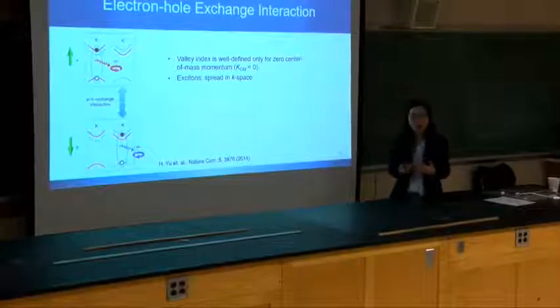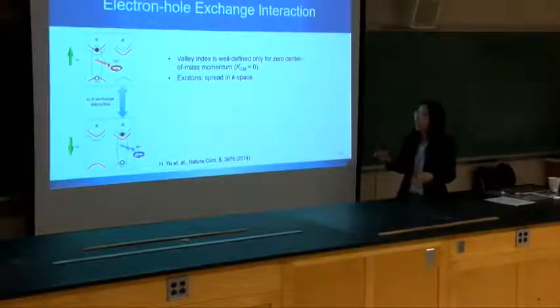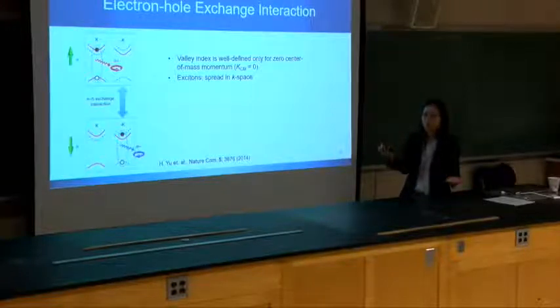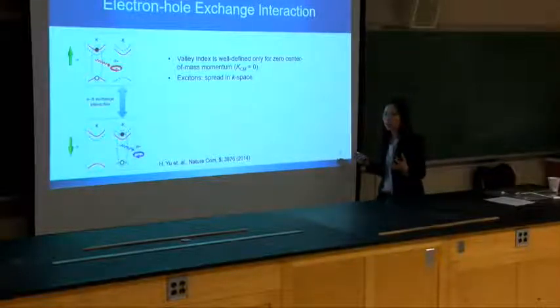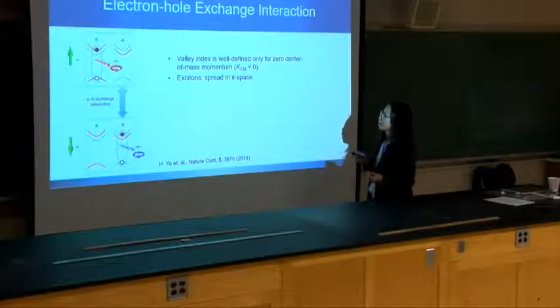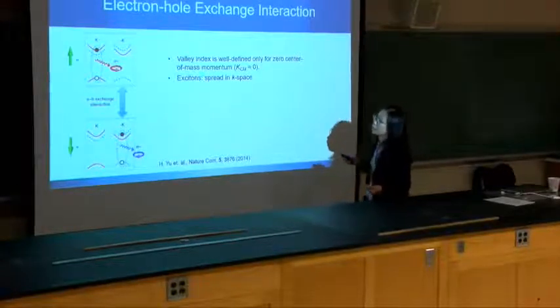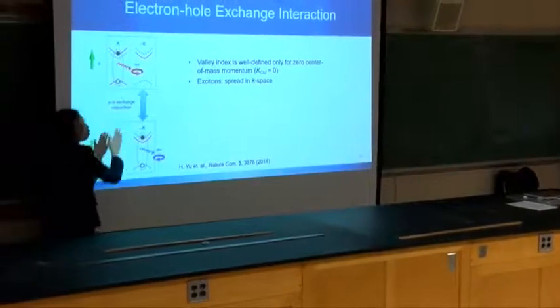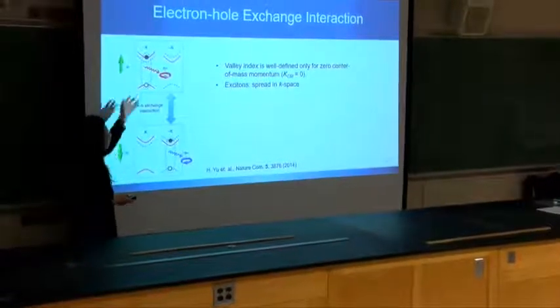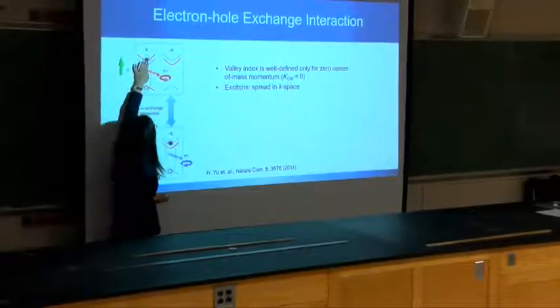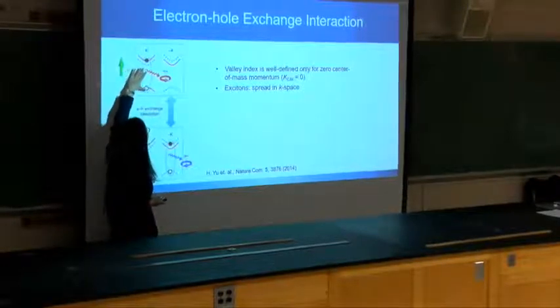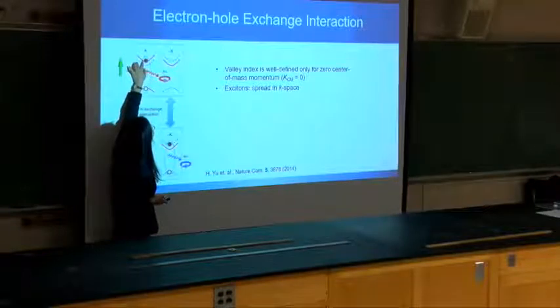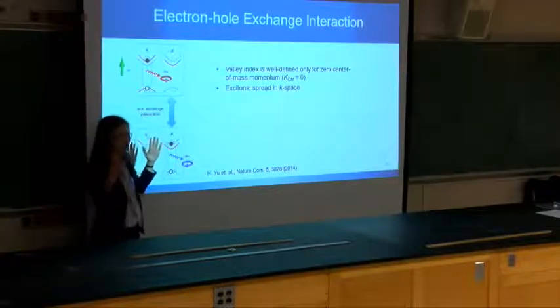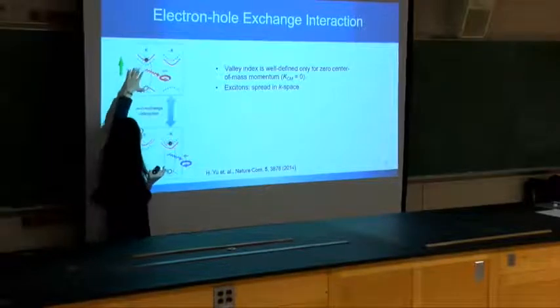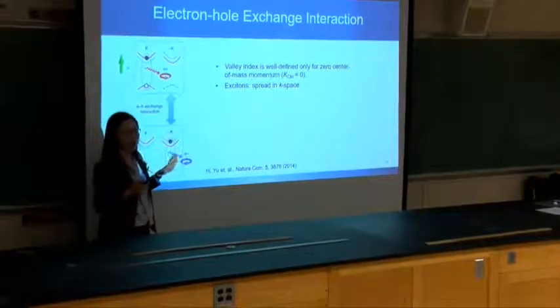Okay, so this is the first part, in terms of optical initialization. Just now I talked about how the valley index is very robust, and it looks like one can really store information by using the valley index. But in fact, the valley index is only well defined for zero center of mass momentum. So what does it mean? Let's say when we create an exciton, an electron-hole pair, if the electron is shifted a little bit, as long as it's within the light cone, it can still emit. But in this case, it will have a finite center of mass momentum.